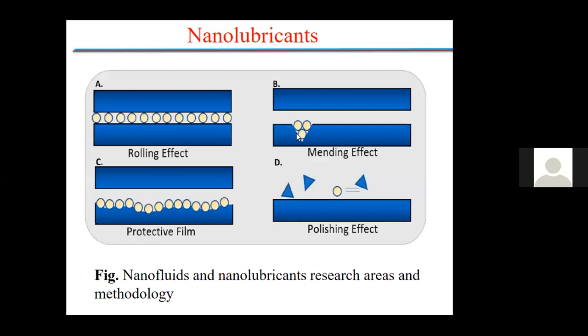So the wear and friction can be minimized. As we say, wear and friction can be minimized by using nanoparticles. We should know how. So we have the rolling effect. In the rolling effect, nanoparticles become rollers in this fashion. These are the two sliding contact surfaces. In between these sliding contact surfaces, the particles become rollers, which minimizes friction. In some cases, it becomes a protective film.